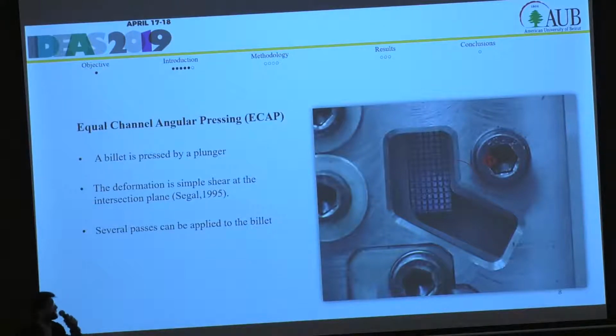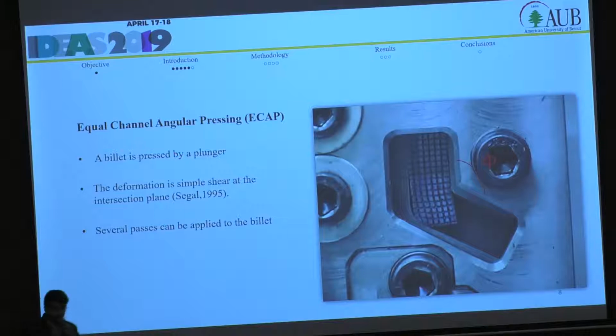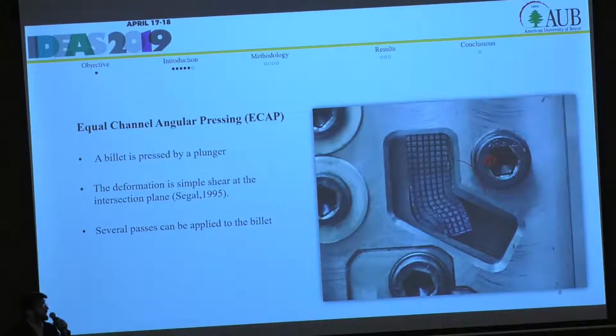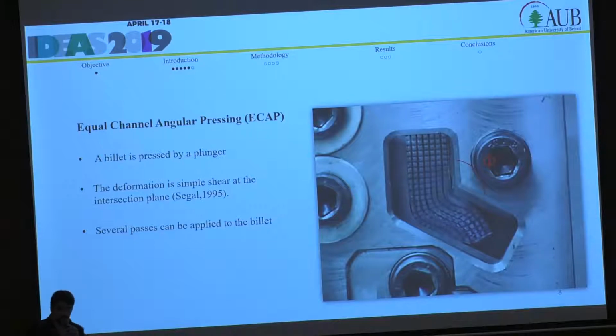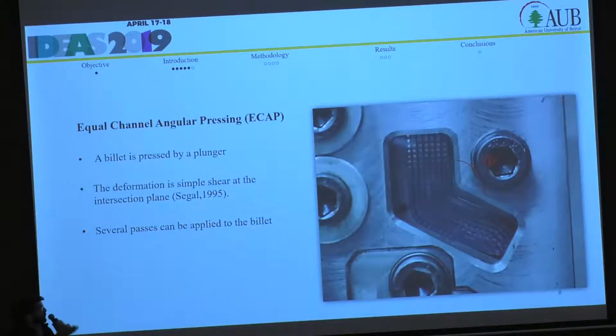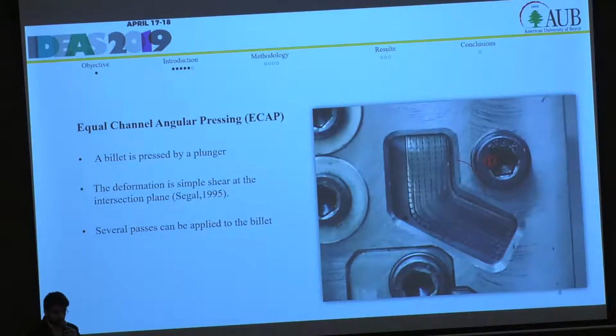So to achieve this plastic deformation, some mechanisms or techniques can be applied. One of the methods is called equal channel angular pressing, where a billet is pressed by a plunger. This process is one of the thermomechanical processes that improves and enhances the mechanical properties. We press the billet between two channels intersecting at a certain die angle phi. So what happens is we have a simple shear at the intersection plane here, and the grains will fragment, and we will have a drastic decrease in the grain size. Also, several passes can be repeated.